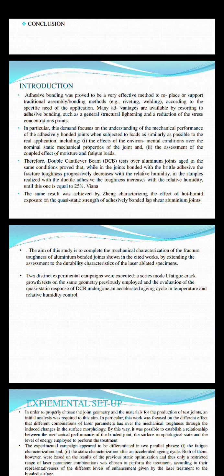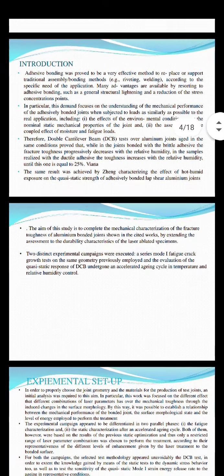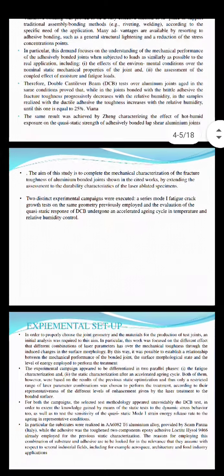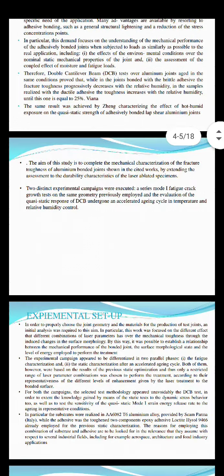Coming to the next point, the double cantilever beam test over aluminum joints aged in the same condition proved that for joints bonded with the brittle adhesive, fracture toughness progressively decreases with relative humidity. In these samples, the ductile adhesive showed toughness at a relative humidity equal to 25%. The same result was achieved in the characterization of the effect of hot-humid exposure on the quasi-static strength of the adhesively bonded aluminum joints.